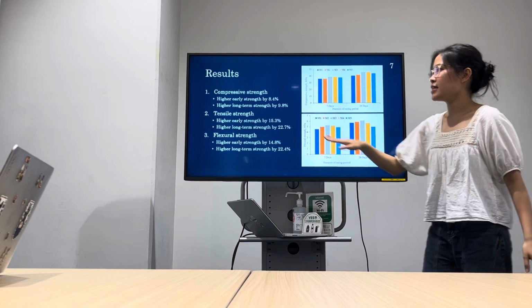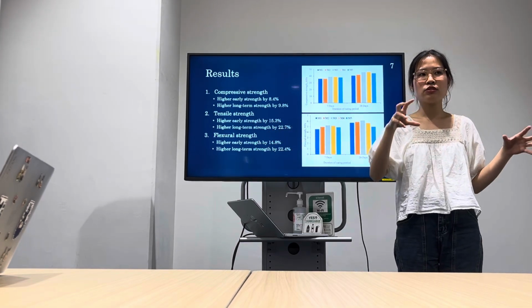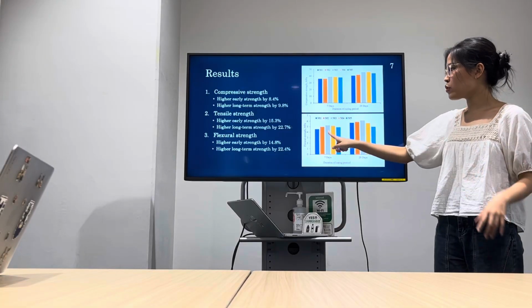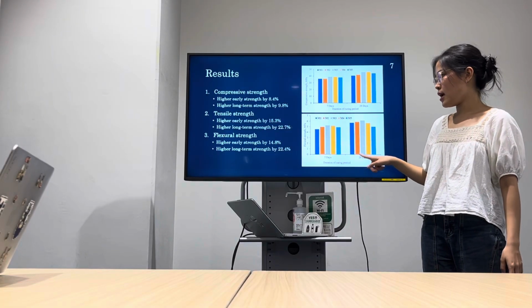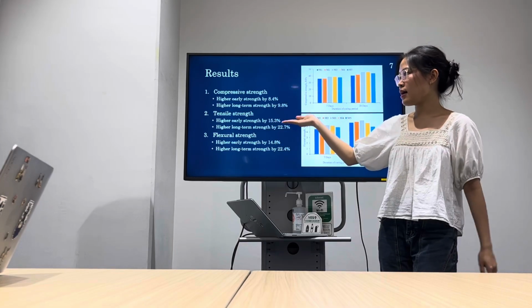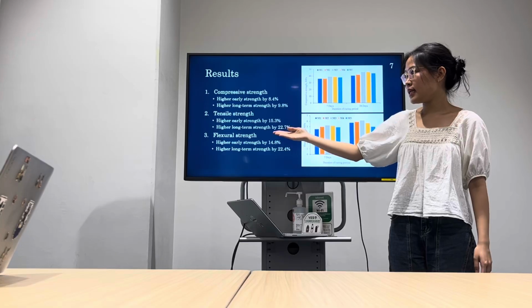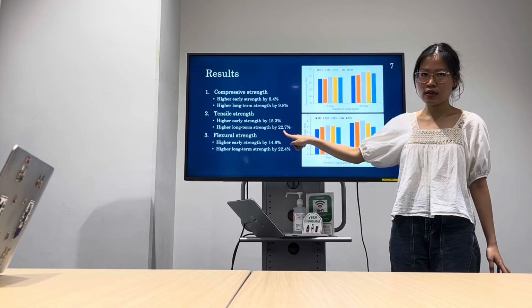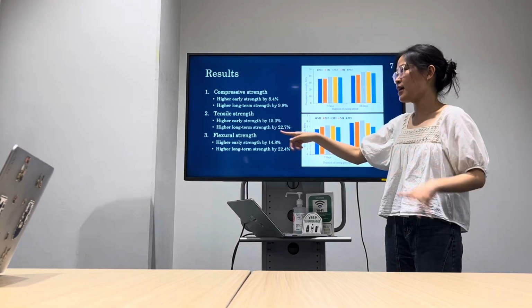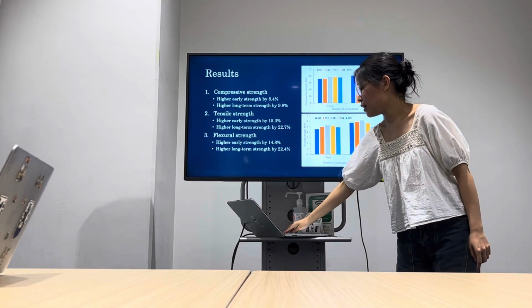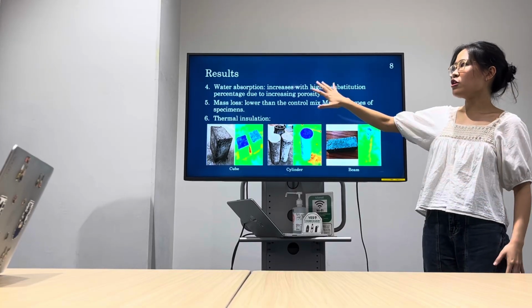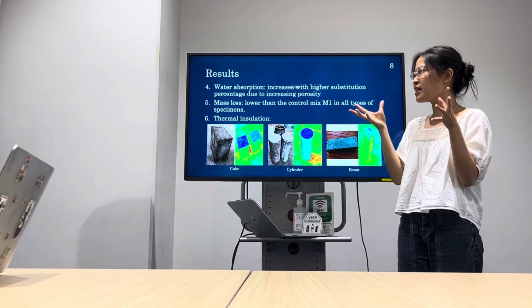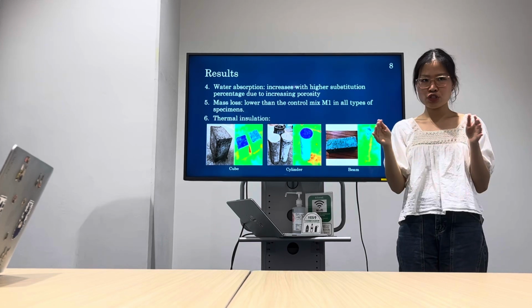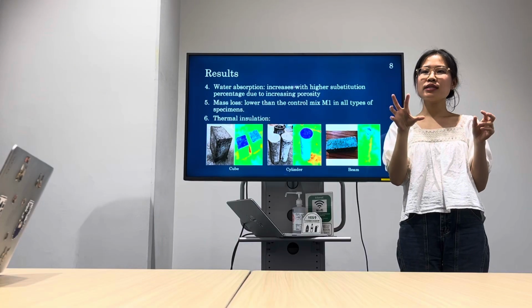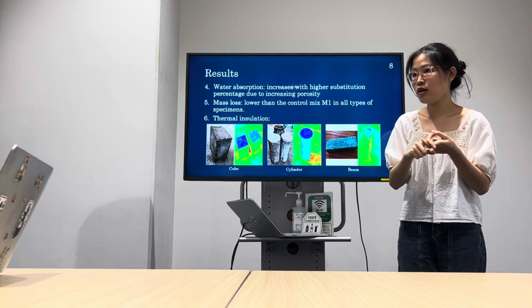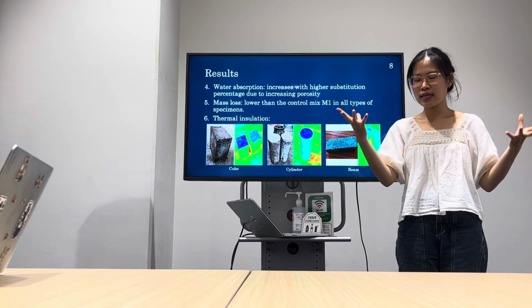So that is good. And then tensile and flexural strength both demonstrate the same kind of pattern, where M3 demonstrates the highest values at 7 days and 28 days. As you can see here, higher early strength by 15.3% and higher long-term tensile strength by 22.7%. And same goes for flexural strength. And then we have water absorption results. Water absorption increases with higher substitution percentage due to increasing porosity. However, the increase only ranges from 0.21% to 0.76%, so that is still acceptable.